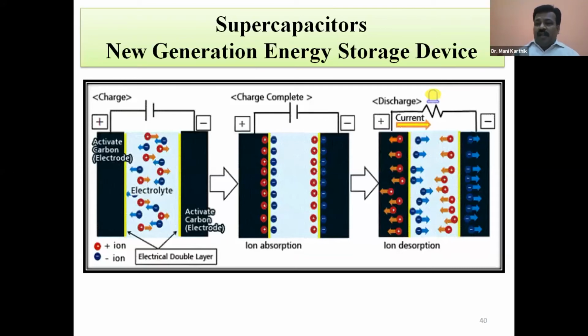Another option is to use non-aqueous electrolytes, with non-aqueous solvents. For example, tetraethylammonium tetrafluoroborate, TEABF4, is a well-known commercial organic electrolyte salt dissolved in acetonitrile or propylene carbonate. With that, the electrochemical window can go up to 3.5 volt. Some people are using LiPF6, lithium hexafluorophosphate. With lithium hexafluorophosphate or ionic liquids, you can go above 3 to 4.5 volt. So the electrochemical window depends on the electrochemical stability of the electrolytes used in these supercapacitor devices.